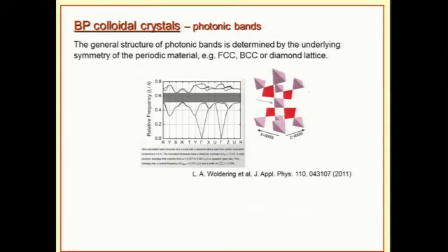And here I'm citing a paper from the literature where they show that if you have a diamond lattice, actually they need truncated tetrahedra positioned into a diamond lattice in order to achieve a nice and wide photonic band gap. So one needs to think hard about how to engineer this material to achieve strong responses.